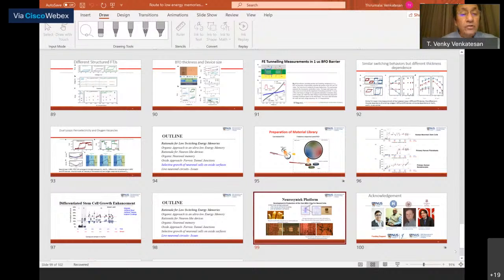So exactly what is the physics of why the chemistry of the surface makes such a difference? I mean, what's the difference between yttrium oxide and zirconium oxide? Why do they behave like night and day? That is still, I mean, it's fascinating. It's very difficult to get the physics out because the system is relatively dirty because there's a lot of water around. You've got the cells alive, you have to have nutrients, sugars, and other stuff. Figuring out the physics of this is very tricky. But on the other hand, we can see trend lines that are very interesting. This is a happening field right now. Study of adhesion to the surfaces. Unless the cell adheres, there's not going to be any growth.